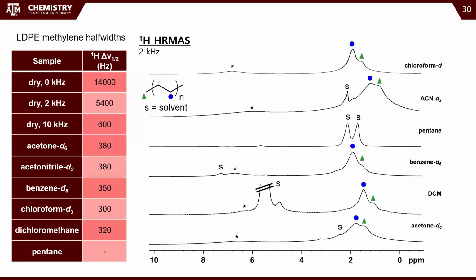So this is proton solid state NMR, which is pretty unusual. Proton has a really high gyromagnetic ratio, and so you have very strong homonuclear dipolar interactions. But we can resolve even the methylene and the methyl peaks. So this is a good technique to use. If you just have a simple material, you want to know the degree of branching, for example, then you can make kind of a calibration curve with a particular solvent that you have. And if you already know the degree of branching, then you can quickly build a library, right? And then you could use that to characterize materials. So yeah, we can resolve both of those peaks, and we have pretty good resolution, double what we see if it's just a dry material, even with the high rotational speed.